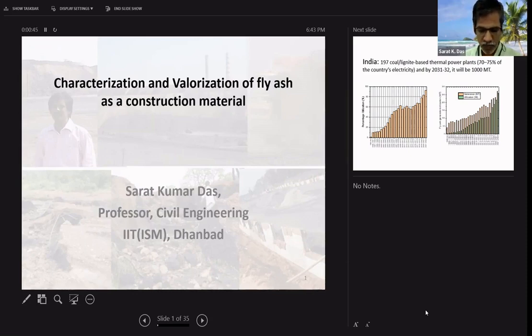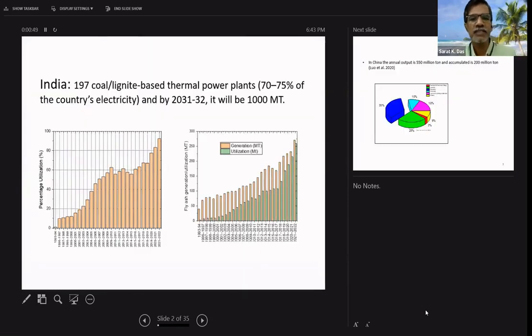Now when I come to this fly ash, I will show you this graph. If you look at this graph, this is about India only. This is the latest 2021 data. So look at the percentage utilization. In 1993-94, the generation was very less and the utilization was also limited to 3%. And as you see, as time grows, the dependency on the thermal power plant in India increased. And then there was a fly ash mission. So after this fly ash mission, between 95 and 2000, its utilization percentage increased. And now, if you see the percentage utilization, it is almost 92%.